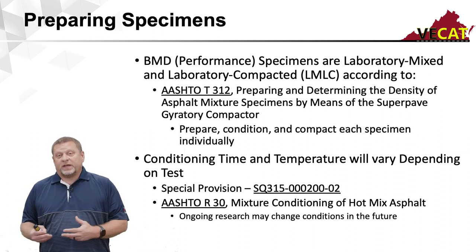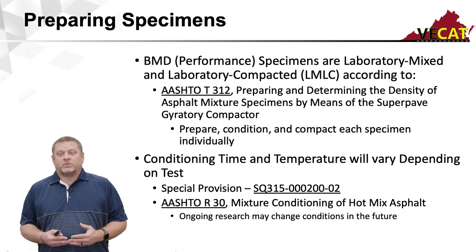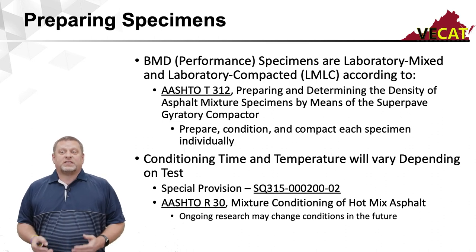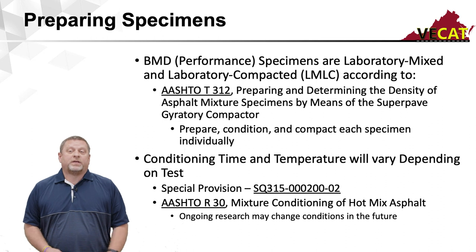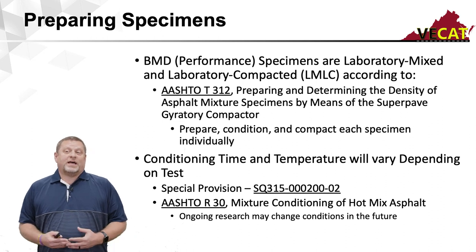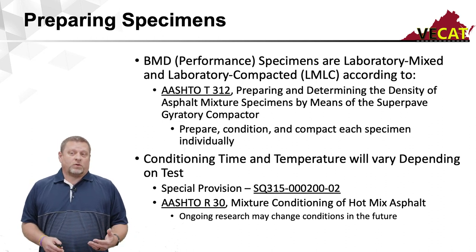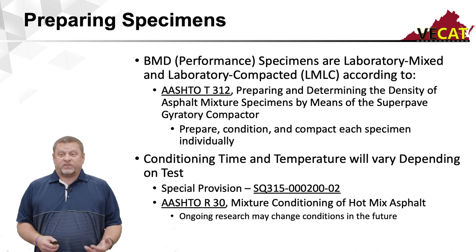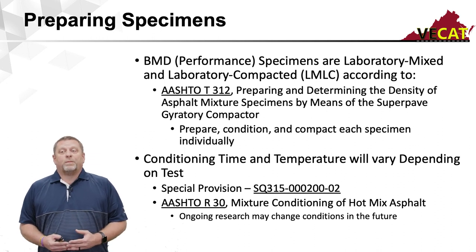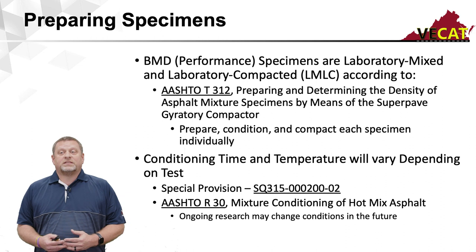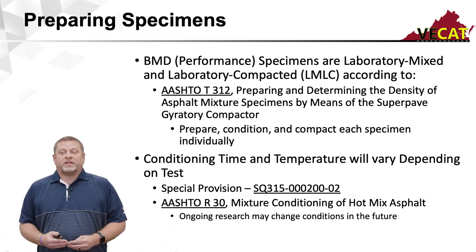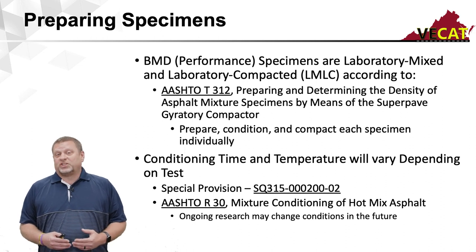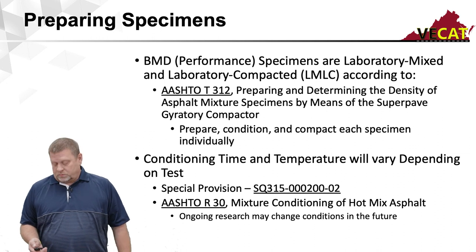Some of the differences you may see based on AASHTO T312 is that the conditioning time and temperature will vary depending on the test. These times and temperatures are spelled out in the special provision for VDOT. But one thing that does remain constant is that you still have to look at AASHTO R30 for the conditioning requirements. There is ongoing research that may adjust these conditioning requirements in the future, so please stay tuned.